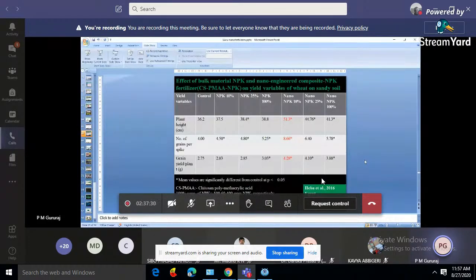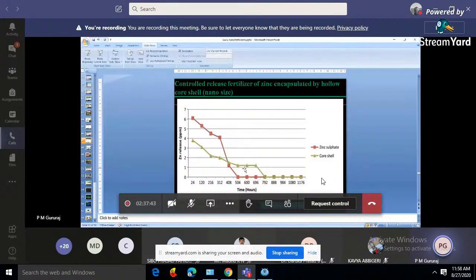What happens is that in the bulk there is no control of the release of a fertilizer. But in the case of nanoparticles, there is control. That means you give one nanoparticle at one time. That is hypothetical, again. I'm saying there is a controlled release of particles in the case of nanoparticles, while there is no controlled release in the case of conventional fertilizer. You can see here, this data indicates zinc release at the ppm level. What you see in red is zinc sulfate, the conventional fertilizer. And the green one is a nano fertilizer.